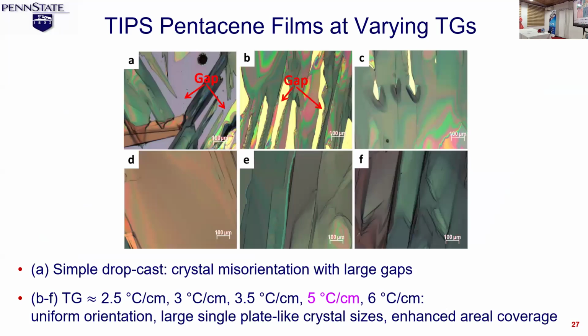Casting, again, you notice that these crystals crystallize in the directions that you want. You have too many gaps. You have these deposits of the TIPS pentacene which we don't want. But then immediately using the temperature gradient method, you start to see good crystal alignment.